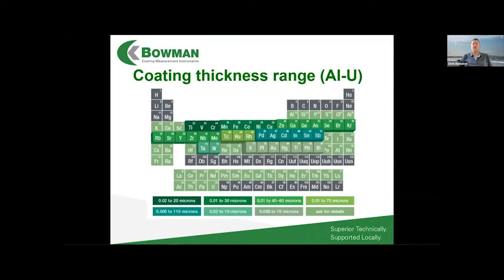Again, getting on the thickness range, because I get asked that a lot. Here's a periodic table showing the different elements and the different ranges at the bottom. As you can see, it varies quite a bit. This is really dependent on the actual characteristic energy of the X-rays that are fluoresced, based on the element. Again, you can see sort of on the low end, if we're looking at aluminum up through around titanium, we can't measure those real thick. But then you get up into something like tin or silver or cadmium, which are pretty common platings, and we can measure those up to over 100 microns in thickness. So it does vary pretty widely depending on the element.